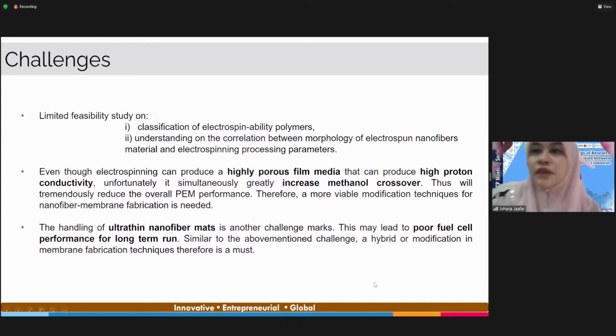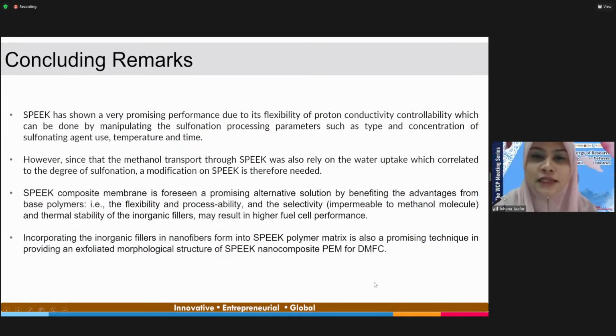As the concluding remarks, SPEEK has shown very promising performance due to its flexibility of proton conductivity controllability, which can be done by manipulating the sulfonation processing parameters such as type and concentration of sulfonating agent used, temperature, and time. However, since the methanol transport through SPEEK also relies on the water uptake, which is correlated to the degree of sulfonation, a modification on SPEEK is therefore needed.